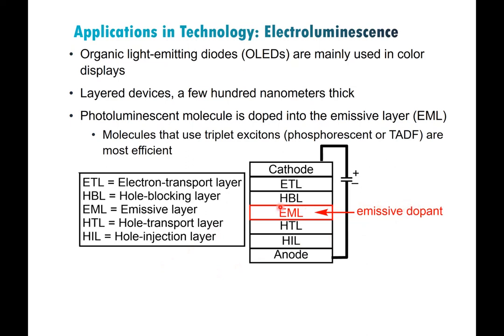Now, for a typical OLED device that uses phosphorescent or TADF emitters, the emissive part is actually doped in at a relatively low level, maybe about 10% or so by weight in the emissive layer. So most of the weight of the OLED is actually the other components. The emissive part is just a small fraction, which is another reason why there's not really much concern with using iridium for OLEDs, because you use a very tiny amount of it compared to the cost of all the other materials that go in. So there's not really a huge incentive there.